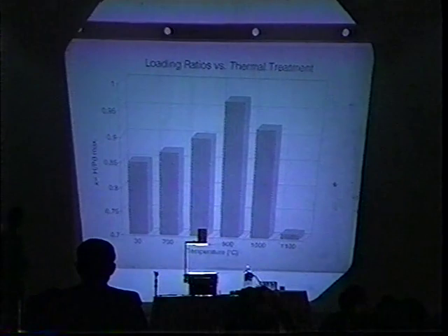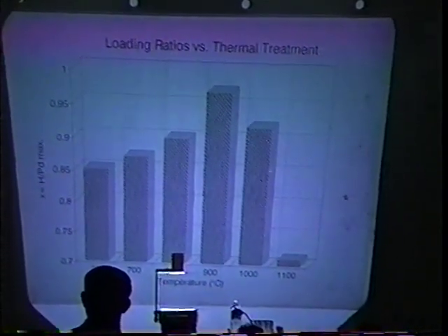And then we expect it to have a different loading condition in such materials. Then the results are summarized in this sheet. As you can see, the best behavior is given by cold working plus annealing at 900 centigrade for 1 hour. The behavior of the cold-worked metal is this one. This, of course, can maybe be improved, because of some problem in the measurement of the loading ratio by resistance evaluation.